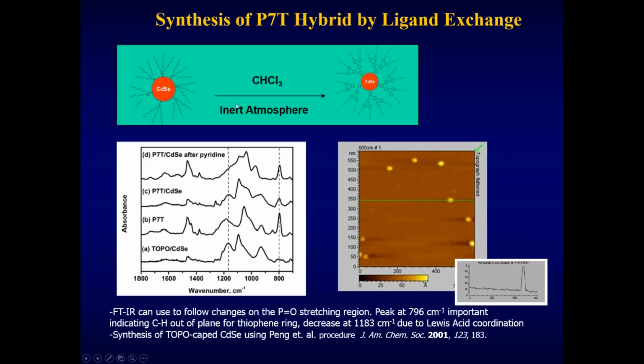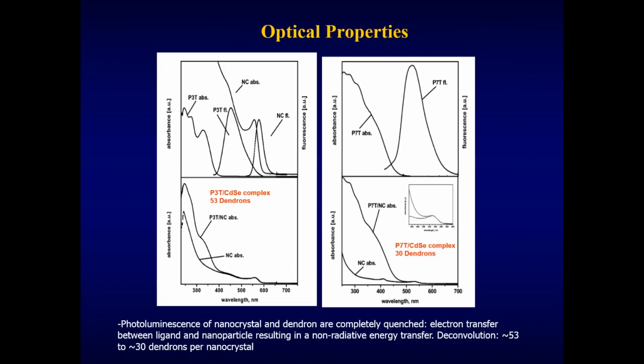Now let me turn to a hybrid complex of a cadmium selenide nanoparticle and a dendron based on polythiophene. So to synthesize this, we started with the synthesis of a polythiophene dendron with a phosphonic acid side group, which can then be used to chelate with a cadmium selenide nanoparticle. By itself, it's an interesting fluorophore, with a fluorescence of around 550 and absorbance up to a 500 tail. And what we did is we indirectly, through substitution, functionalized it on a cadmium selenide particle.